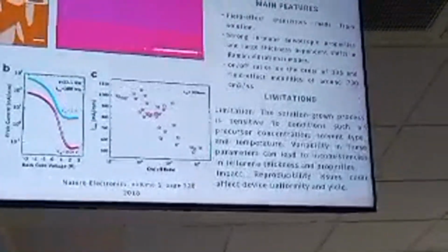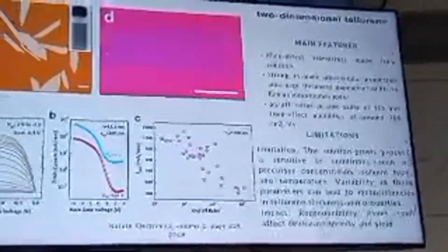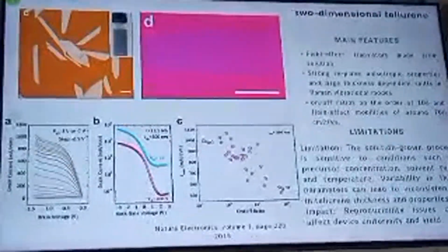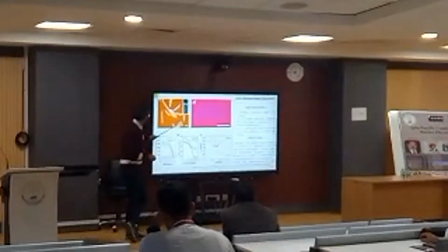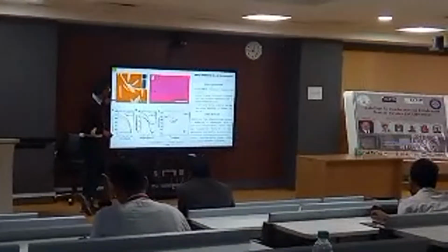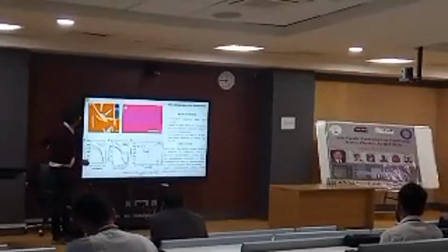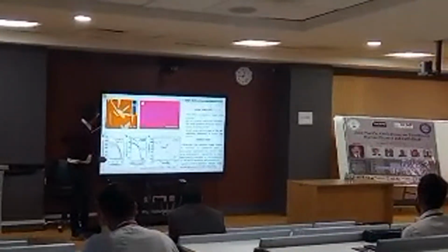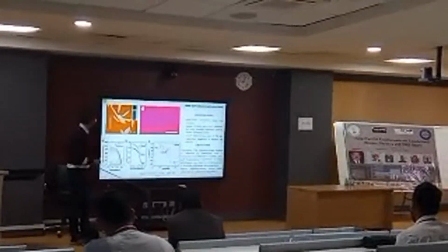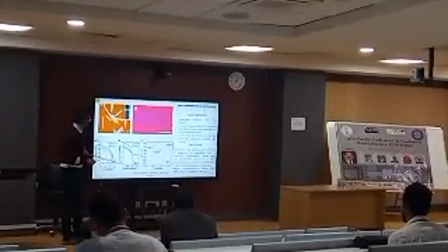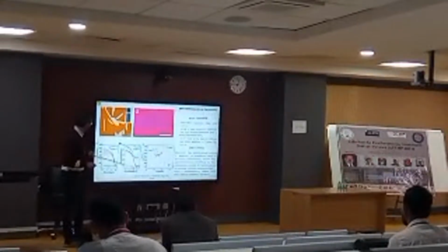Okay. So, to introduce our system, the most recent work I could find is this 2-dimensional tellurene, where people chemically found a solution process, with drain voltage, and then you could see this tellurene. It's flat, and from this solution you can create these flakes, drop-cast them on silicon oxide, and create this FET to find the transfer characteristics like back gate and drain current.